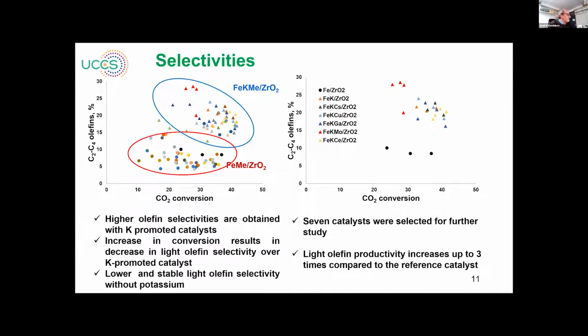The next slide shows maybe the most interesting result which we obtained, relevant to selectivity to light olefins. And what was found here, there are 2 trends. First trend was observed for the catalyst which doesn't contain potassium. Here the selectivity to light olefins was relatively low, I would say between 5 and 10%. And also it doesn't depend on the conversion. It remains almost the same. However, for the catalyst promoted with potassium, which contains, of course, different elements, there is this trend. So the selectivity is initially higher. However, of course, it decreases when we increase the conversion.